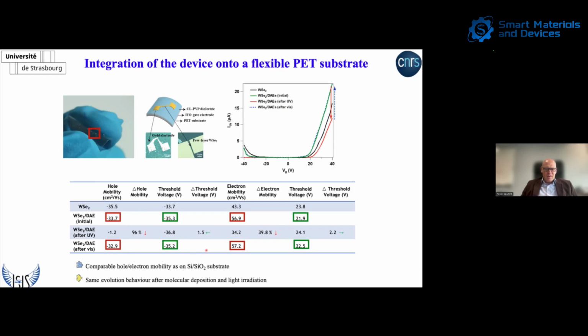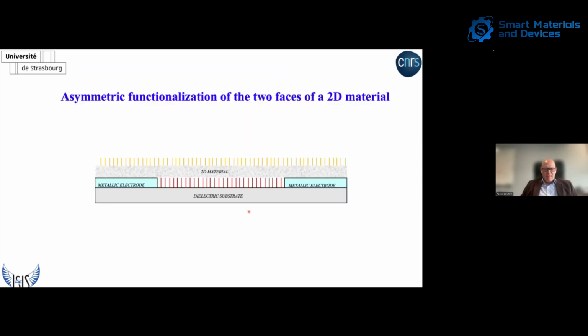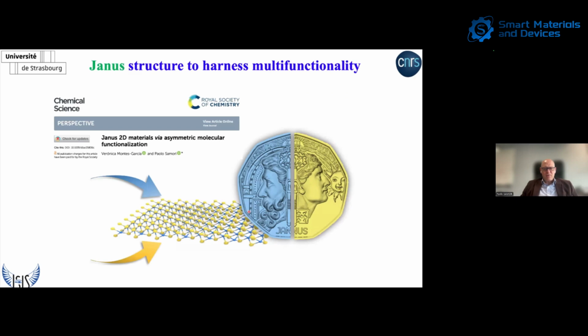And so you can see here. Now, this is quite interesting because it is important for considerations in the context of ambipolarity and having more sophisticated devices that try to imitate CMOS-type devices. Another consideration is that the two-dimensional material structure is very well defined, and you have a bottom surface and a top surface that can be asymmetrically functionalized. So we use a kind of Janus approach to boost the functional complexity, exposing the two faces to different local environments.